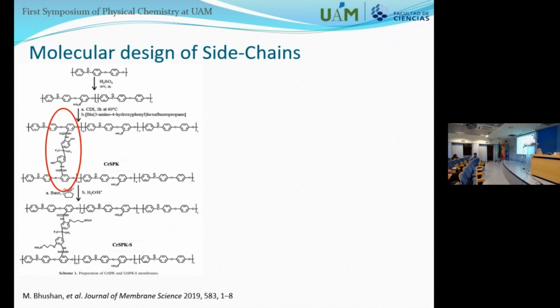But usually, when we do the cross-linking, we are using some of the anion exchange groups that are present in the membrane. Because of that, we are losing part of these groups, and then we are reducing the ion exchange capacity, which is linked to the conductivity. So if we lose ion exchange capacity, we lose conductivity, and it works in a worse way. But in this work, working with the side chain, the linker that they are using, of course, consumes part of these groups, but also has the possibility to be further reacted to produce other sulfonic acid groups in the side chain. So we are losing some of the groups in the main chain, but we are adding other ones. We are getting both things: the cross-linking, and also compensating for the loss of the ion exchange groups that we had.